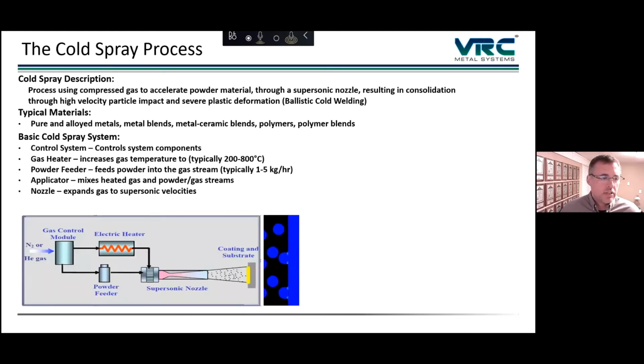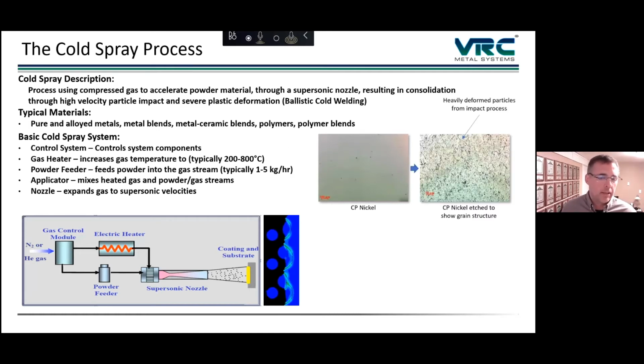The system consists of pretty simple components: a control system, heaters, powder feeder, applicator nozzles. And this is all to get that acceleration of the powder particles, as you see, impacting on the surface and causing severe plastic deformation. When you do it right, you get a deposit that's relatively featureless. But if you etch it, you can actually see that severe plastic deformation within the particles themselves.